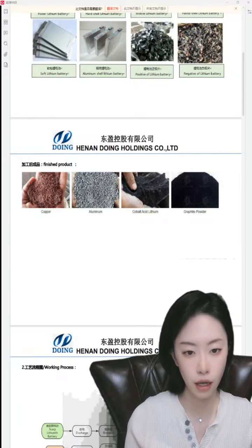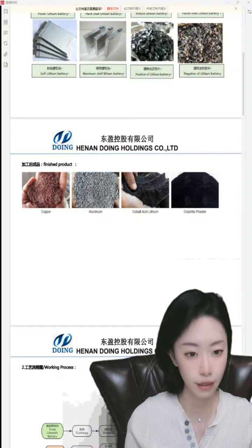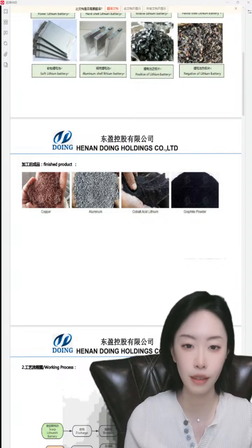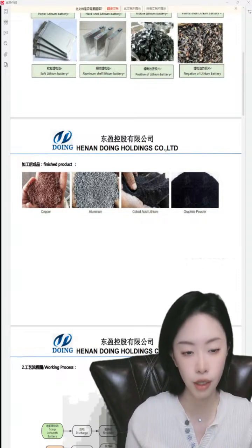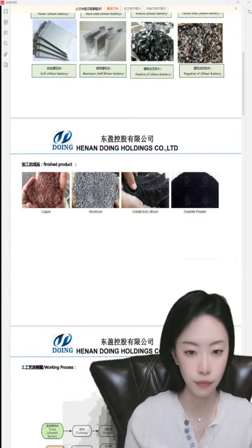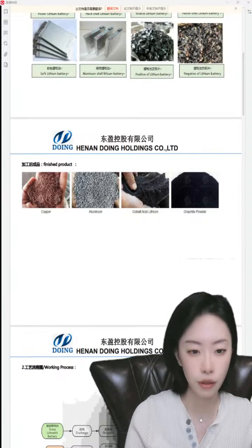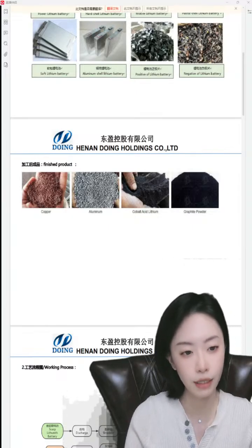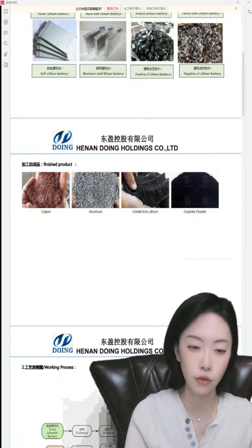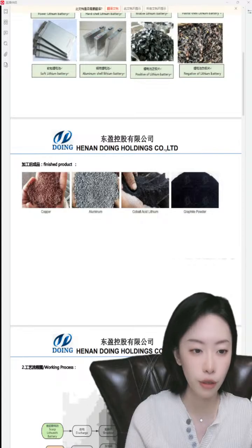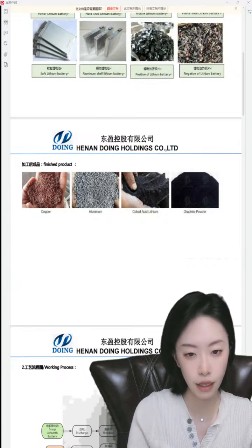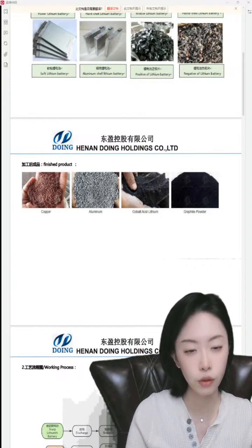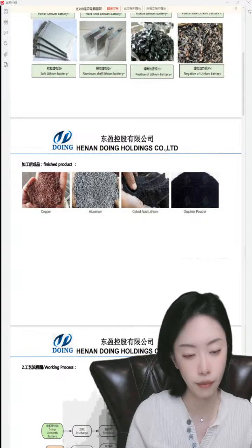And by the way, we also have 3 to 5% of plastic. And if your raw material is hard shell lithium battery, we also have 3 to 5% of iron. The product's purity of the black powder is above 98%. The size is about 140 mesh. The proportion of copper and aluminium content in black powder is within 2%. And we also have the powder of copper and aluminium, and the separation rate can reach 98 to 99%, and the size is 30 to 50 mesh.